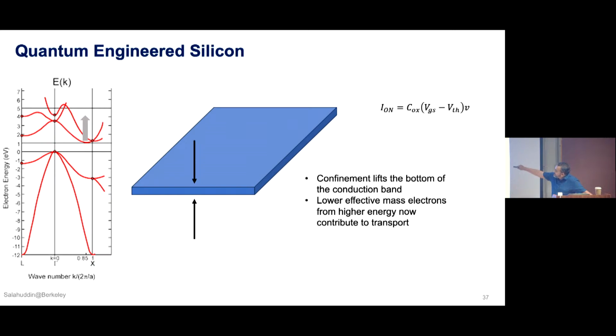And as it starts to go up, your effective bandgap is going up. But at the same time, these higher energy electrons start to contribute to the transport. And these higher energy electrons have lower effective mass. So in principle, if you thin down the silicon, the velocity may actually go up. Okay? So without understanding the implications of this, as a grad student, I did these calculations, mostly to show that this becomes a direct bandgap material. But in those calculations, it was already known that the overall velocity actually goes up.